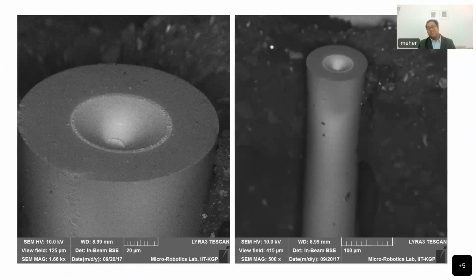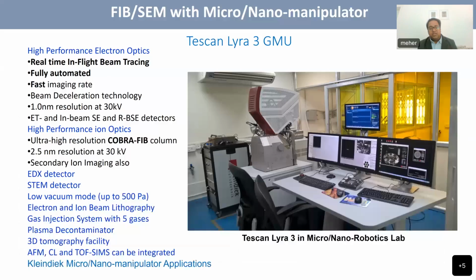But it was very tough because the fiber was made of glass, and we were using gallium ions. Using gallium ions for etching the fiber was really very challenging. You can see here the equipment which was used for these experiments. This is focused ion beam lithography equipment having gallium ions, and it also has manipulation capability. In this system, we can single-handedly pick a nanofiber or nanoparticle and place it somewhere in a very controlled manner. Although I'm saying it very easily, it's not simple to do,